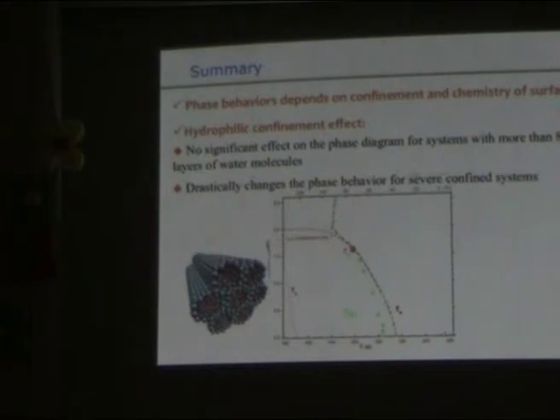We also check the interplay between confinement and the surface chemistry. You can see that, first of all, you can look at the highly confined and the less confined. They are plotted on the same scale. For highly confined, of course, it's shifting to high pressure. Okay, and for different surface chemistry, this is really confined. This is super hydrophobic, and this is hydrophilic. You can see that hydrophobic moves to lower temperature and high pressure. So they both play a lot of roles. Okay, so this means the confinement data is not straightforward. You cannot apply it directly on top of this bulk data.